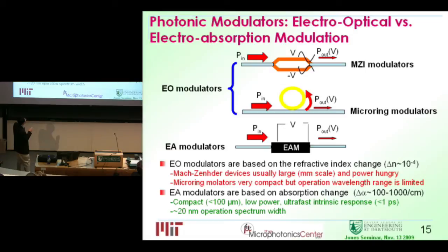You just put the material in between your input and output waveguides and apply the bias, and you can turn it on and off. And this is a pretty large effect, because your absorption coefficient change can be 100 to 1,000 inverse centimeters. So it's a very compact device, less than 100 micron long. Associated with that are low capacitance and low power consumption. And the intrinsic response is very fast. It's a field effect, so the response time is intrinsically less than 1 picosecond. That's 1 trillionth of a second. So this is a very efficient technique to get high-speed modulation at low energy consumption. In terms of operation spectrum range, it's usually around 20 nanometers. So you can operate in a spectrum range, and if you divide the spectrum, you can do wavelength division multiplexing.